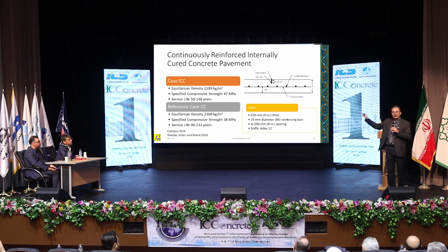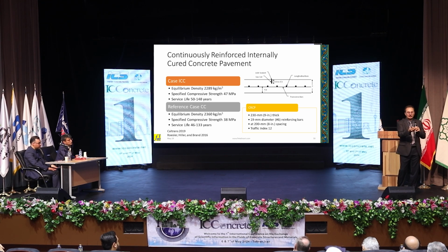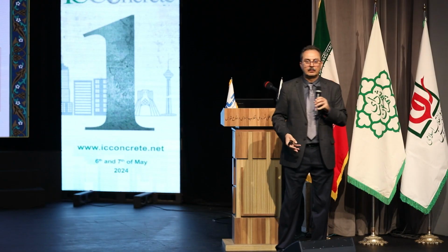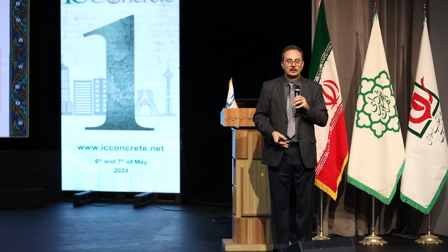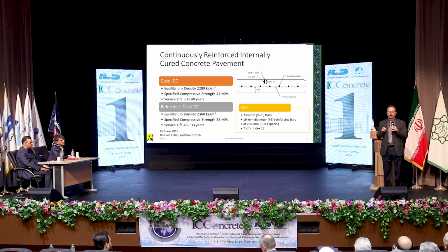So what do we do? We put fine lightweight aggregate that can absorb up to 15% of their weight in moisture. We submerge them for 72 hours to make sure the water goes in. We replace a certain amount of the sand, which can be calculated with that value, with that lightweight aggregate. So when the cement wants to get cured, there is a fine lightweight aggregate next to the cement within that 2 centimeter region. So we hydrate the concrete from inside out.